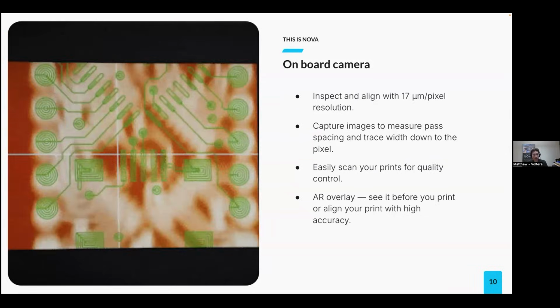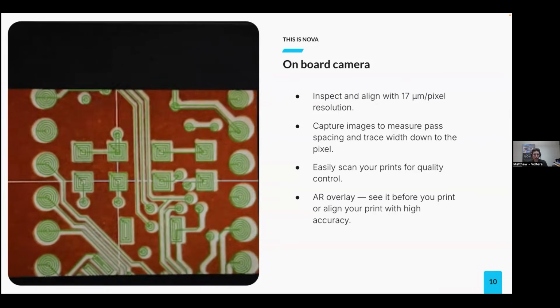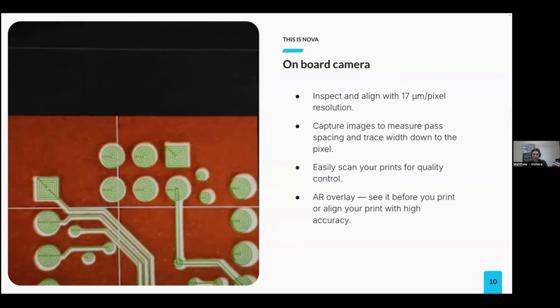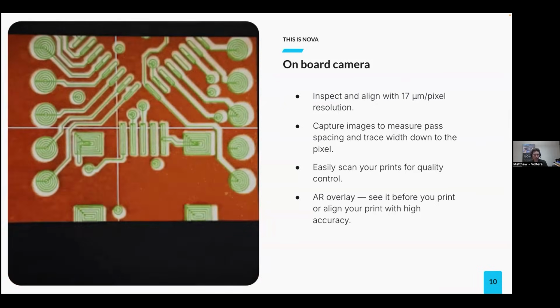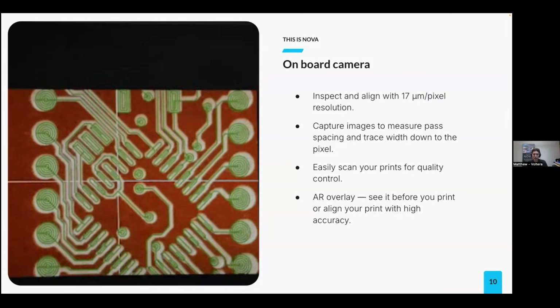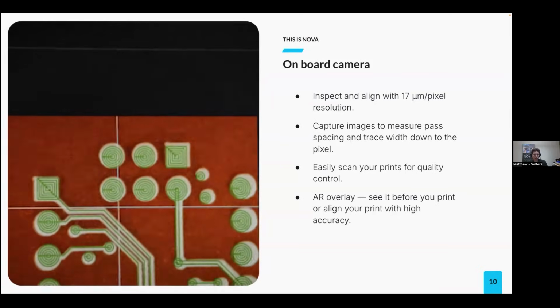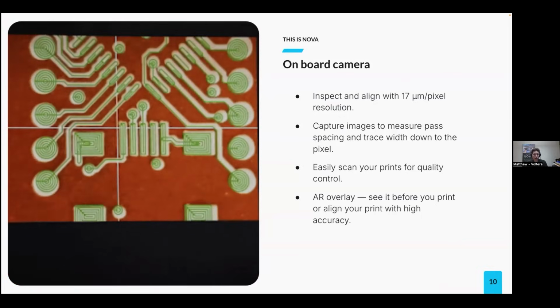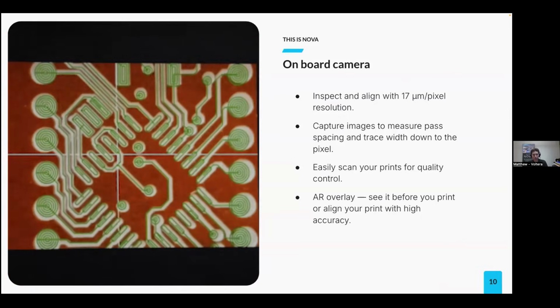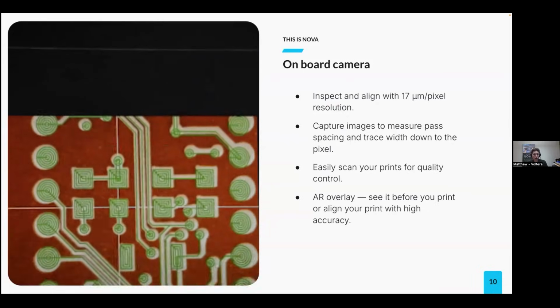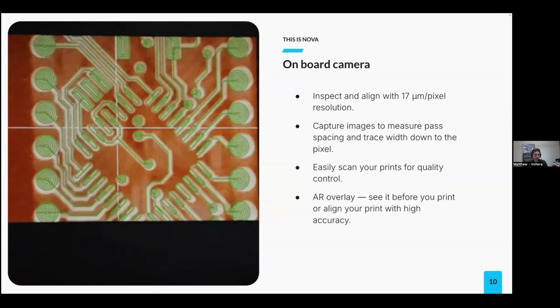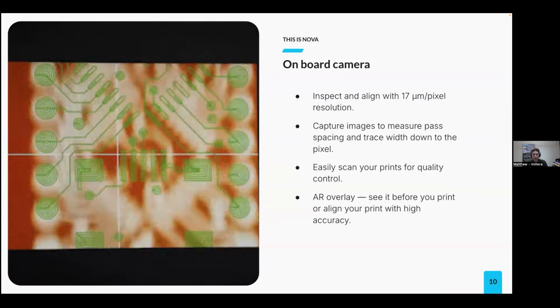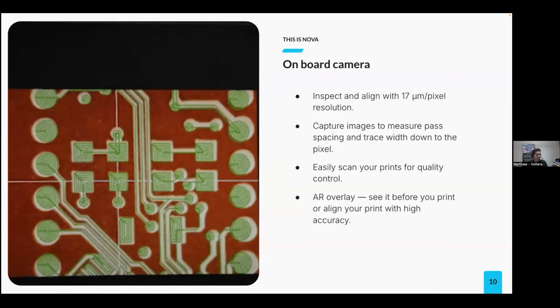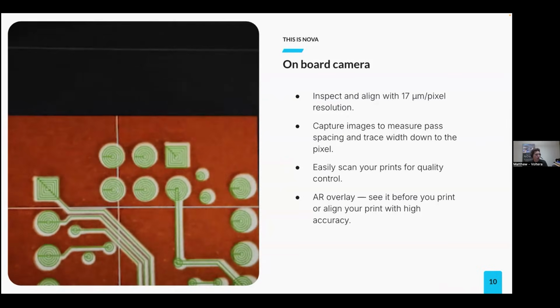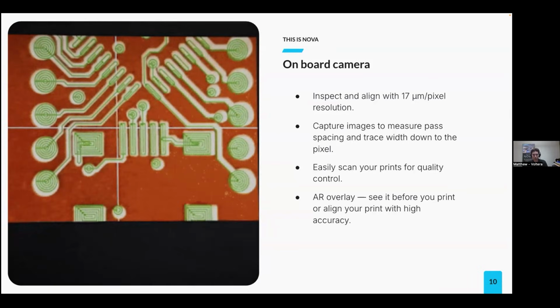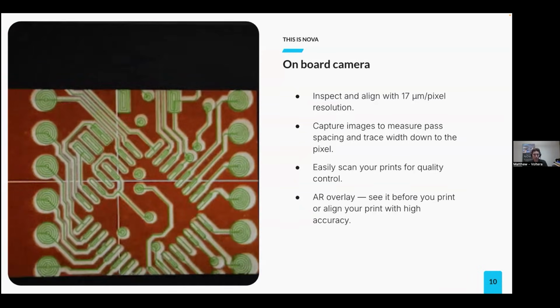Nova has an onboard camera. This onboard camera allows you to inspect and align with around 17 micron per pixel resolution. You can capture images to measure pass spacing and trace width down to the pixel, and you can easily scan your prints for quality control after the fact. Nova's AR overlay feature, which you can see in this slide image, allows you to see your design before you print it and actually enables you to have a much easier and accurate alignment process with pre-existing features on your substrates.